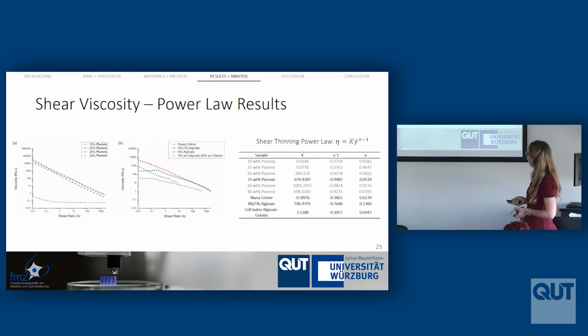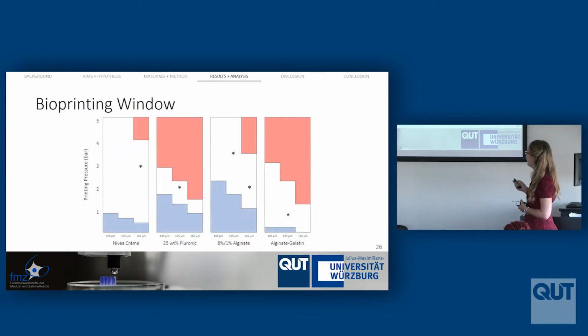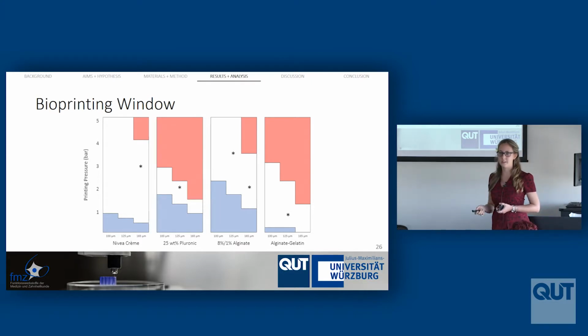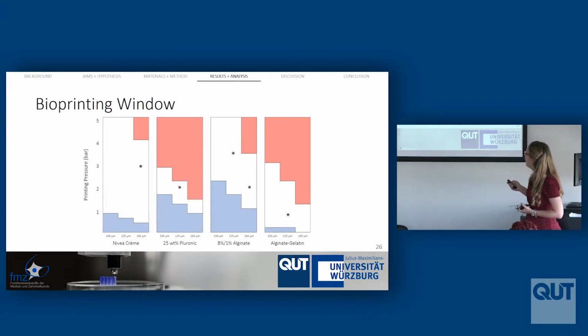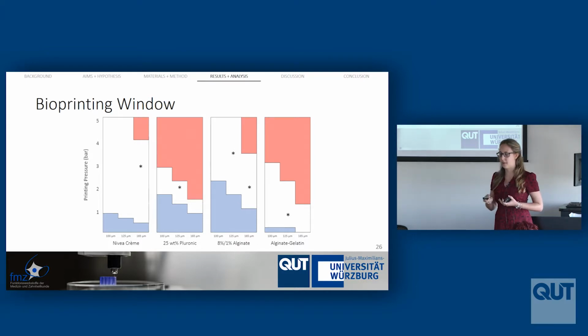And so what this tells us is that there's a very specific range in which the materials can be printed. So for the Nivea cream here, looking at some different needle sizes, and then different printing pressures up here. With very low printing pressures, this is unable to be printed. There is a window here where we're able to successfully extrude that material into the shapes that we want. And then there's a window up here where the material's just flowing out far too fast and we can't catch it in time to make some fibers.